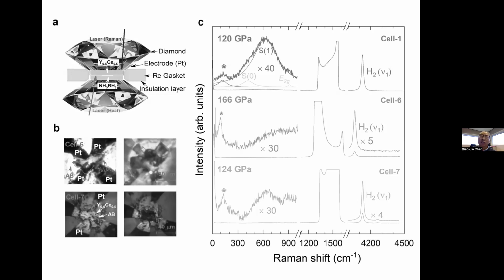while we maintain a high transition temperature. We choose to dope with something like yttrium or lanthanum. As a try, we put an alloy with a component ratio like 1 to 1. Here is Y, like C, the 1 to 1. You can see we synthesize using a procedure Zhu and Ross used. We put AB, like NH3, BH3, as the hydrogen source.